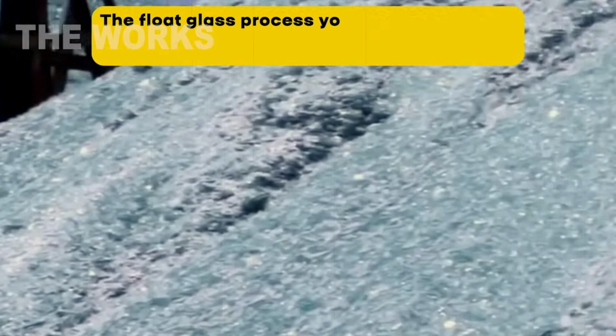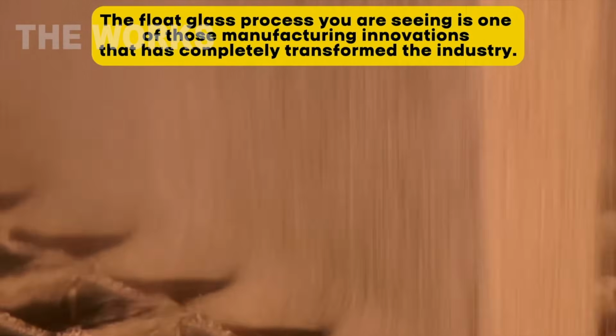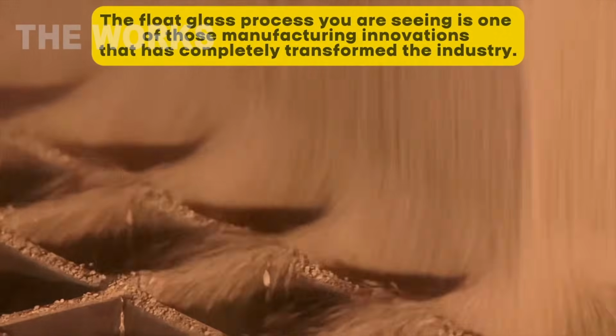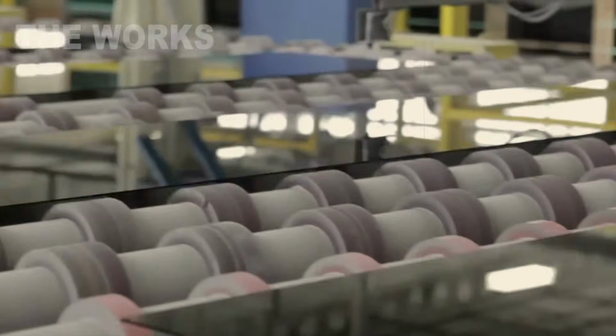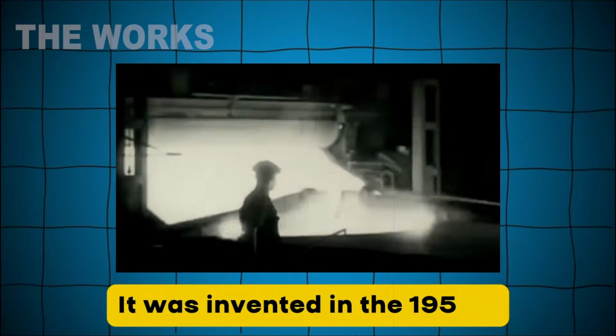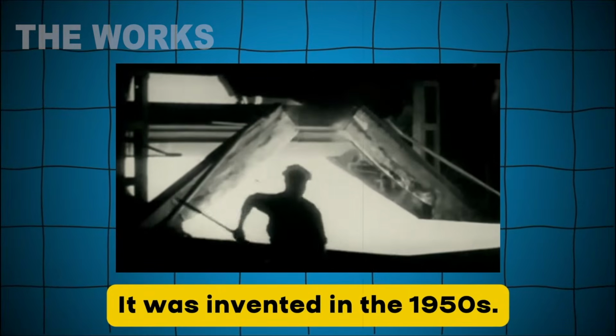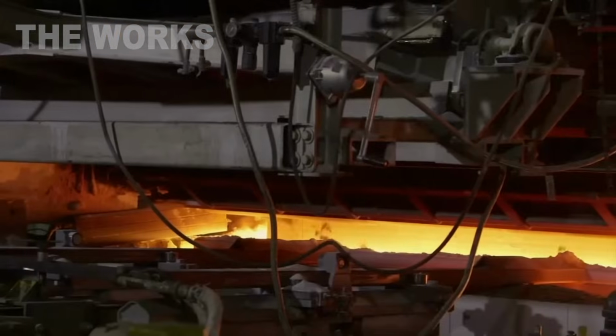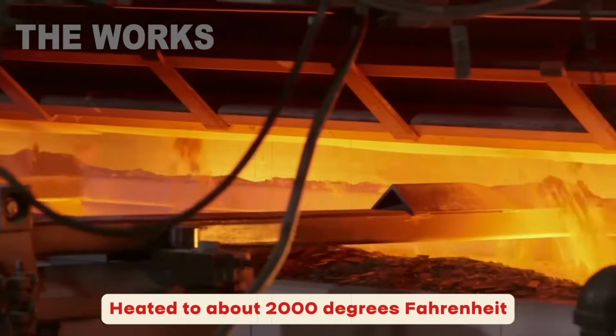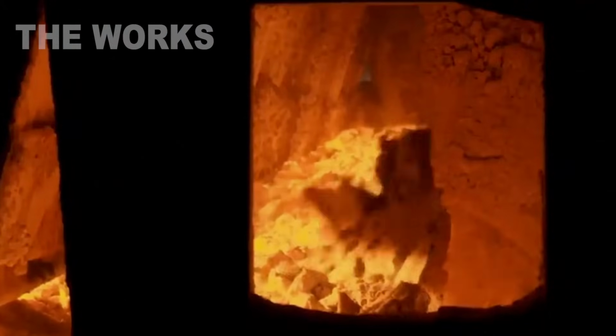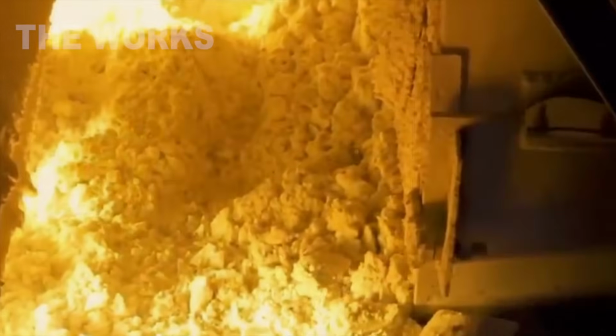The float glass process you're watching is one of those manufacturing breakthroughs that completely transformed the industry, and remarkably, the core principle hasn't changed since it was invented back in the 1950s. Here's how this incredible process works. Molten glass, heated to around 2000 degrees Fahrenheit, flows continuously from the furnace onto the surface of a molten tin bath. The glass literally floats on the tin, spreading under gravity and surface tension, forming a ribbon with parallel surfaces and uniform thickness.